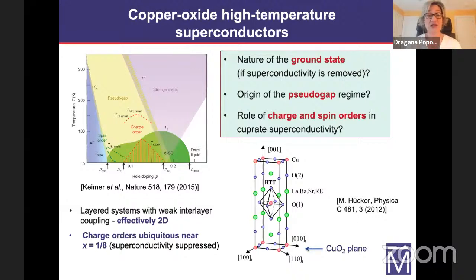Also in recent years, there has been a lot of effort on trying to understand the role of charge orders, which are now established to appear in all hole-doped cuprates, and they're most pronounced around 1/8 doping, where Tc is suppressed. This interest was largely driven by the possibility that the vanishing of charge orders at high doping may be related to these putative quantum critical points that may be responsible for the behavior of the material in this cone-shaped strange metal region. In addition to charge orders, there are also other orders.